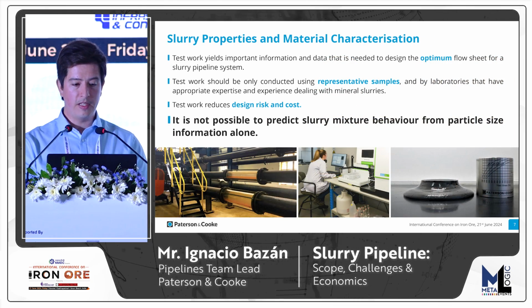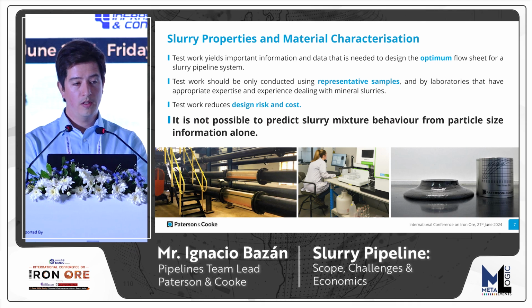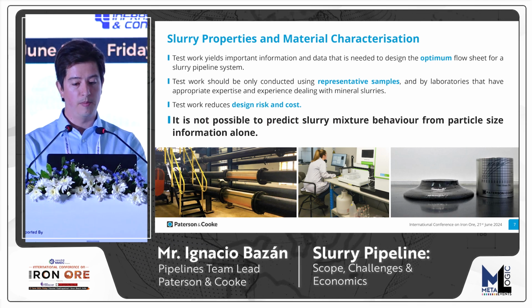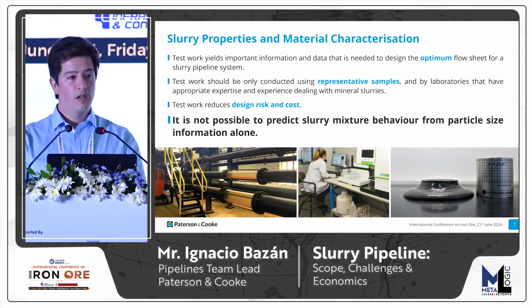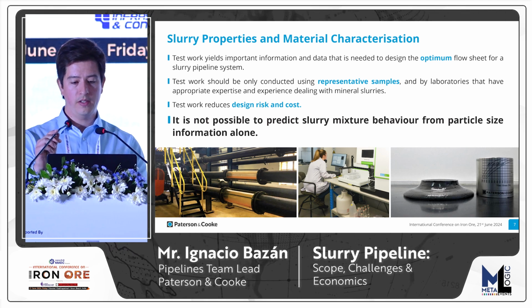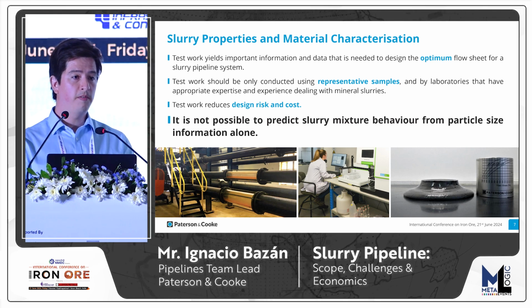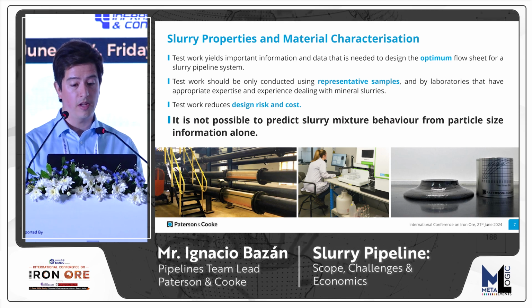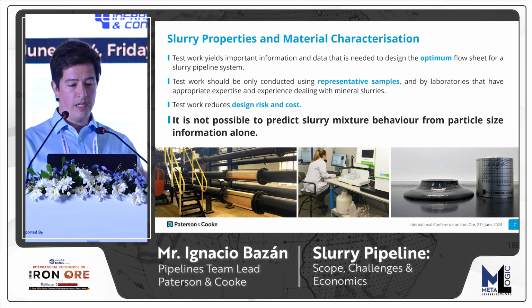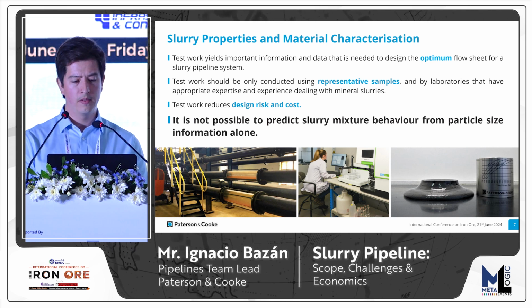So in slurry properties and material characterization, we always insist that the test work is needed in order to be able to design the optimal system. The test work should be conducted using representative samples and by laboratories that have experience dealing with these mineral slurries. As Mr. Rao said, sometimes mineralogy can change, and this affects not only the rheology, but also solids density, which is then a function of the solids concentration. Therefore, your density can have a variation, which is important to capture. And as you can imagine, test work reduces the design risk and cost because it reduces the uncertainty that you can have.